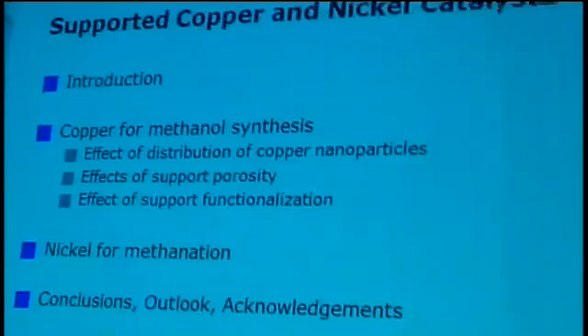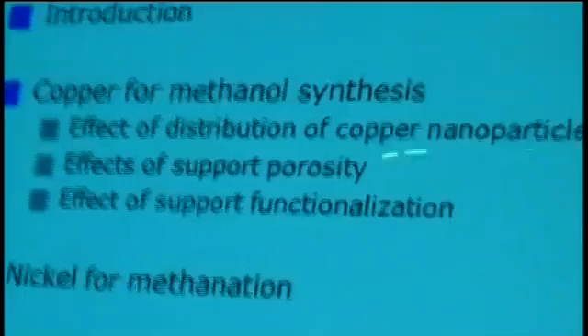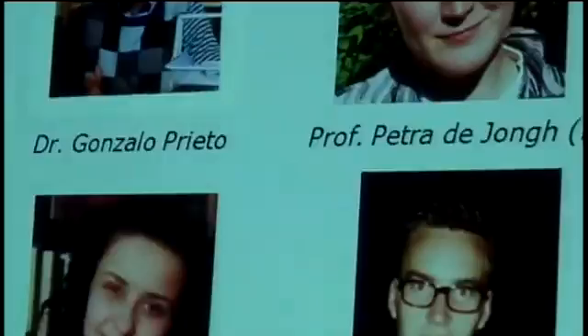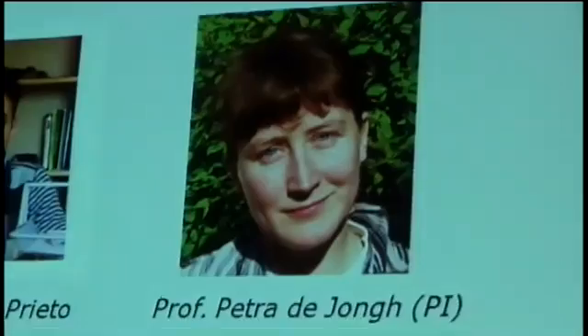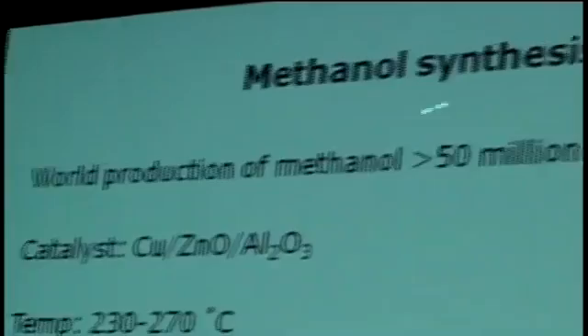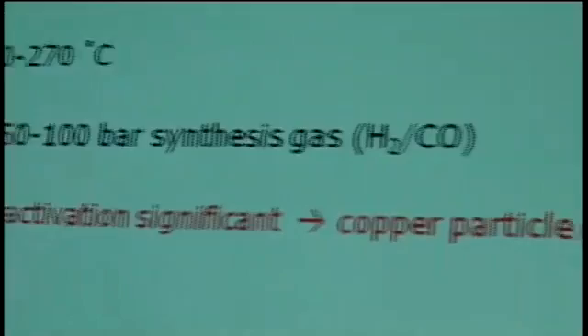Now let's look at copper for methanol synthesis, and we will discuss three aspects: the distribution of copper nanoparticles, the effect of support porosity, and support composition affected by support functionalization. Methanol synthesis is a very important process, with world production over 50 million tons per annum. The typical catalyst composition is copper-zinc oxide-alumina, with temperature and pressure ranges as indicated. Catalyst deactivation is significant and largely caused by copper particle growth.